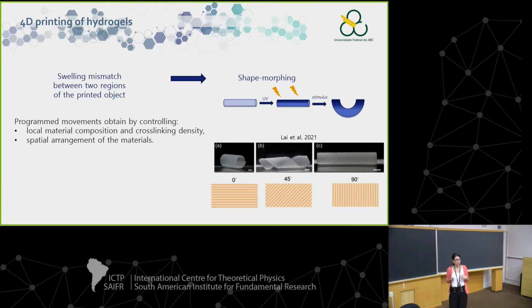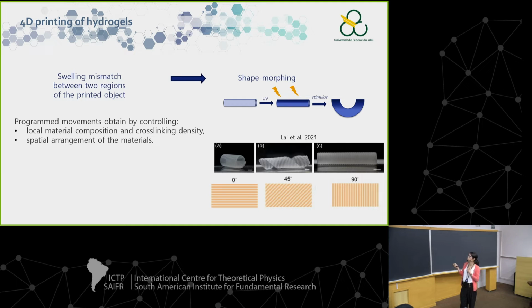But to get this fourth dimension, we need a swelling mismatch between two regions of the printed object. So this creates a stress, and so the structure is able to change its shape. This swelling mismatch can be obtained in just one filament. You expose it to UV, and you will create cross-linking gradients. So on the top, it will be more cross-linked than in the bottom. Then you place it in water under a stimulus, and the upper part will swell less than the bottom part, and you have such kind of movement.